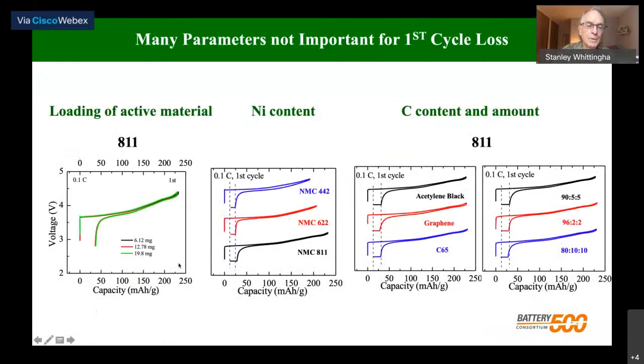So we looked at a number of parameters and we found a number not important, so I won't go into any detail on these. The amount of material had no effect at all. The nickel content, again, from 40% to 80%, had no effect at all. The type of carbon we used had no effect, and the amount of carbon we used had no effect. So it's something inherent to the layered structure itself.